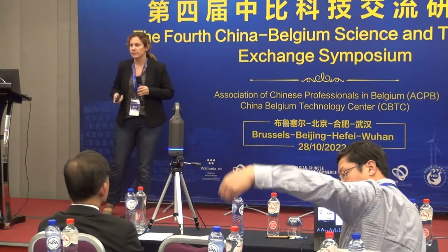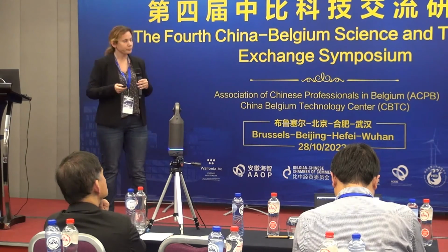Some case study, because the title said that we go for unique properties, so let's start with high temperature properties and fire resistance. So, in my previous slide, I said how inorganic polymer can be made. Now, if you play with your mix design, then you can end up with a mixture that has different behavior at high temperature. You can end up with a material that has quite low melting points, which you can maybe use as glass ceramic, or as a glaze, or you can make the mix design in such a way that you end up with passive fire protection boards or even refractory materials. How do we do it?